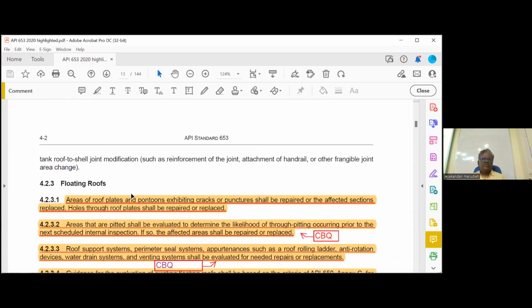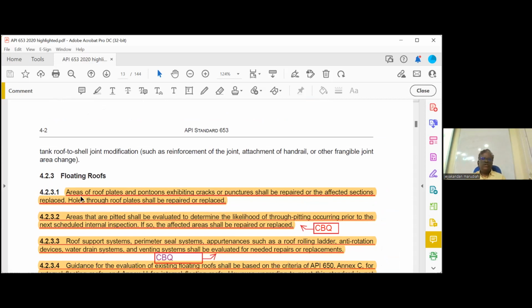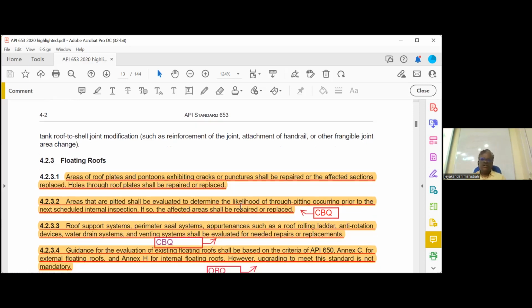The next page, floating roofs. Highlight this one, 4.2.3.1. Areas of roof plates and pontoons exhibiting cracks or punctures shall be repaired or the affected section replaced. Holes through the roof plate shall be repaired or replaced. Any cracks you have to repair. You can all guess this. That's not a very sticky thing. The next one is important. Areas of pitting shall be evaluated to determine the likelihood of through pitting occurring prior to the next scheduled inspection. Suppose there is pitting, we have to check whether it's only a small pitting or deep pitting. If deep pitting, you think before the next inspection it will become a hole, then we have to fill it. How will we repair the pitting? By welding. If so, the affected area shall be repaired or replaced.